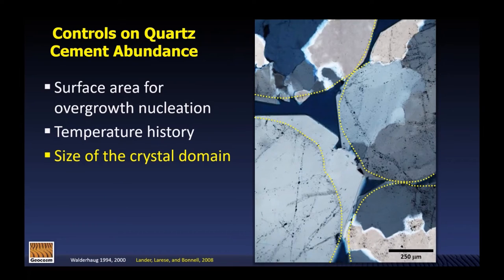And if you're interested in this, we have a paper in 2008 in the AAPG Bulletin that goes into this in more detail. What's neat, actually, is that this thin section photomicrograph shows that very effect that we were talking about. Take a look at this grain right here in the lower left. This is a single quartz crystal domain. It has its c-axis pointing out into the pore space, and we have quite a thick quartz overgrowth here. Now take a look at this polycrystalline grain. We have one small quartz crystal domain right here. It also has its c-axis pointing out into the pore space, but notice it has this euhedral form and has grown much less, even though obviously we had the same pore fluid and same temperature conditions across the span of this pore. So this is an effect that we can readily observe in nature.